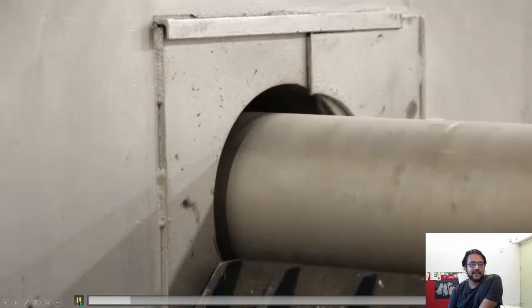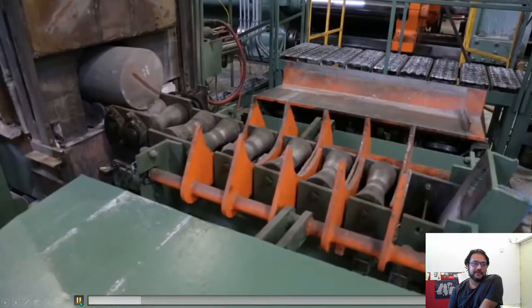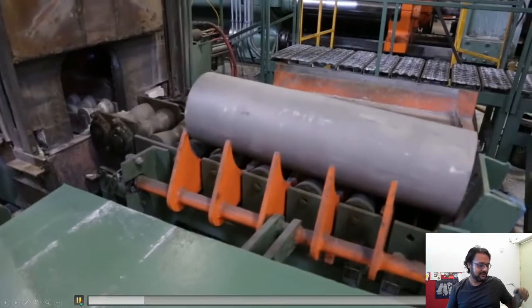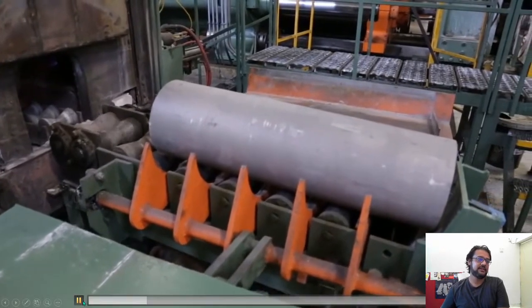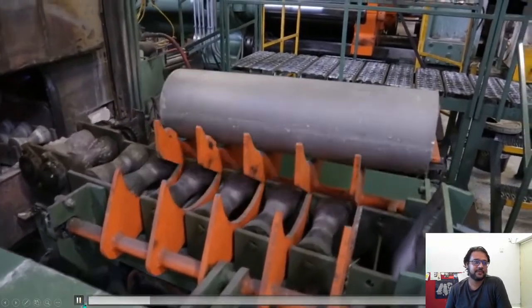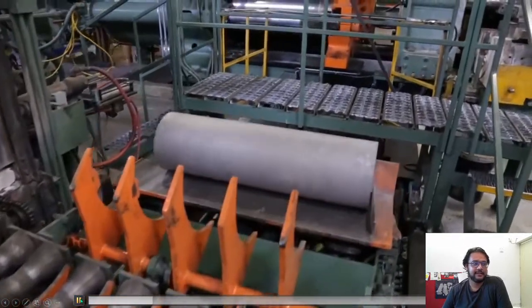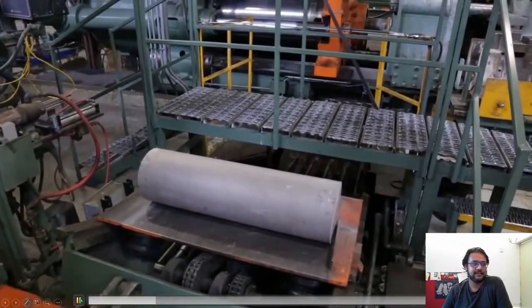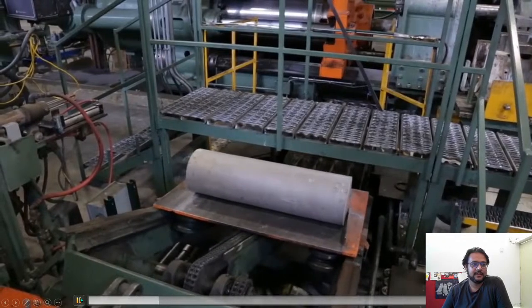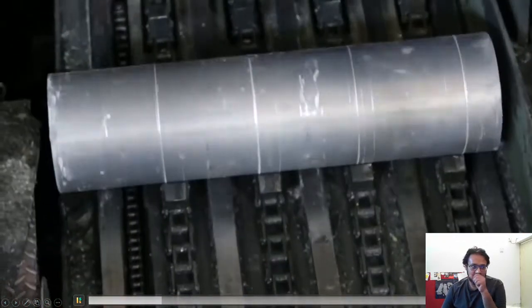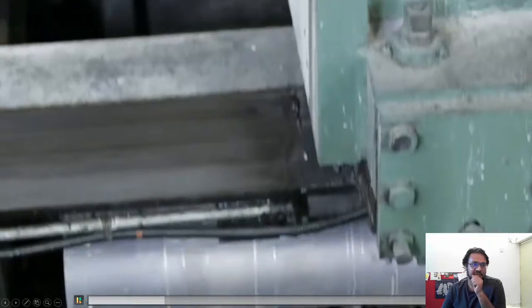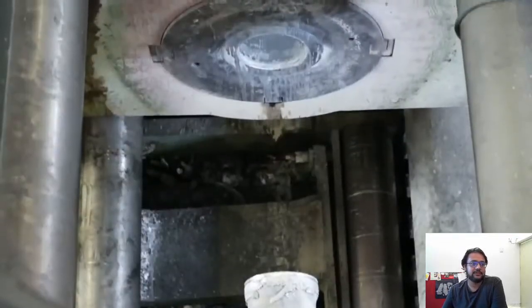6063 and 6061. The log or billet is fed into an oven, which heats the aluminum up to around 900 degrees Fahrenheit. So this brings the billet aluminum to a plastic state, where it is malleable under extreme pressures, but not molten. The log exits the oven and is sheared to an extrudable length, usually about 30 inches, depending on the shape being extruded. The hot 30-inch billet is fed to the extrusion presses by the extrusion loader.